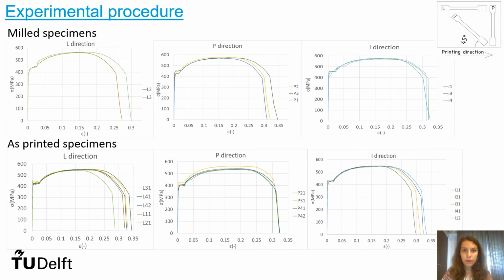Finally, I obtained all the stress-strain curves for milled and also as printed specimens cut in the longitudinal, perpendicular, or inclined direction to the printing direction. They are very similar up until the ultimate strength, and after that they start to be a little bit different.